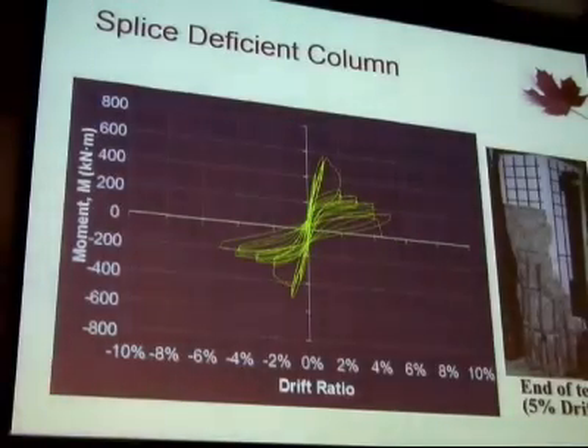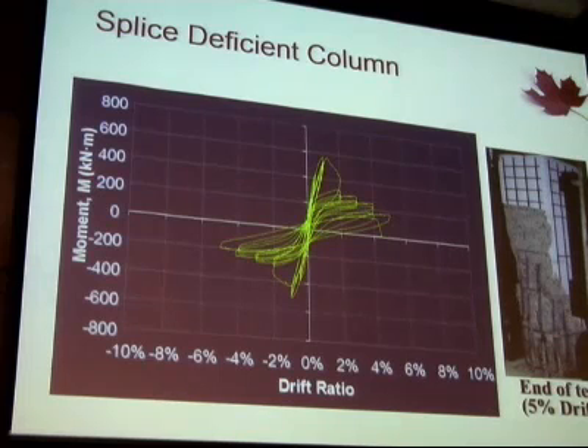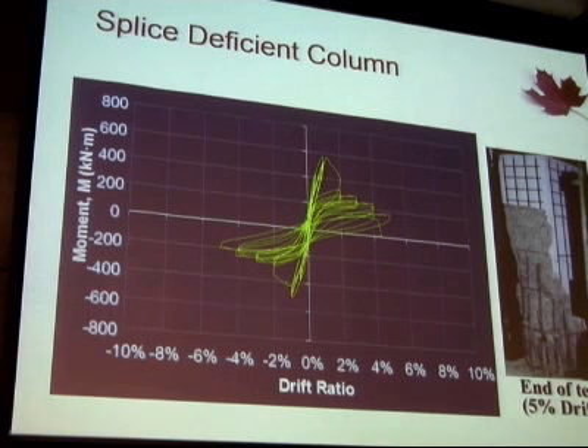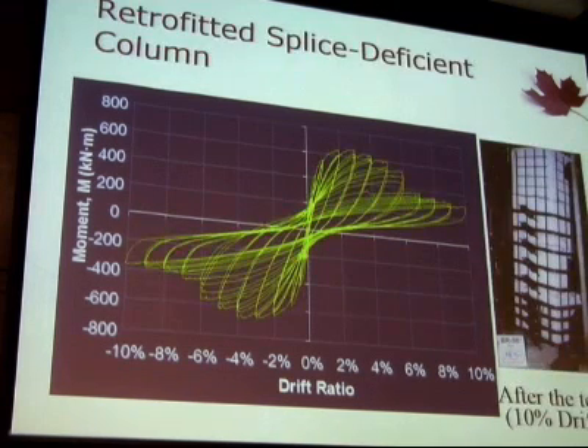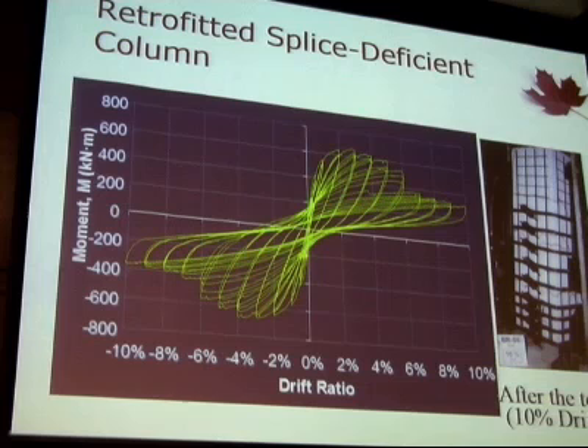Now, the third application is for inadequate splice region, and here's a bridge column which had typical pre-1970s practice with 20 times bar diameter located in potential plastic hinge regions. Beyond 1% drift, bars started slipping. You could see the pinching in the hysteresis loops, and then obviously there was a strength decay. An application of transverse pre-stressing improved bond between steel and concrete and enhanced performance.